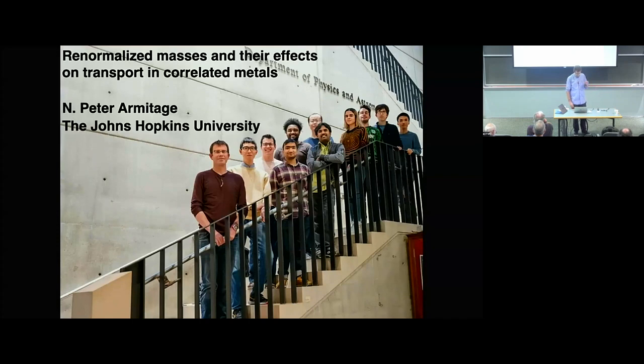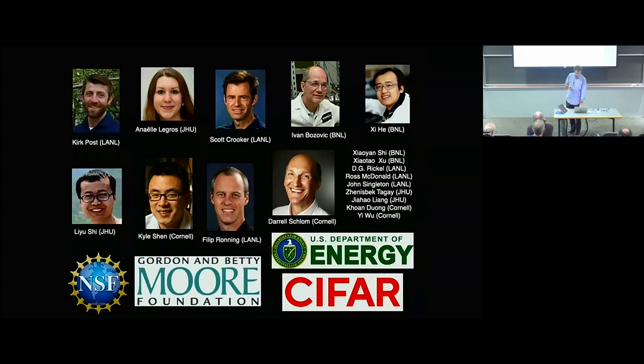And I'm also going to tell you about recent terahertz spectroscopy measurements that we've done on a heavy fermion material, cerium cobalt indium 5. And point out that measurements of the very low frequency conductivity reveal features that show that this system can be interpreted as being consistent with being a Fermi-liquid despite linear in T resistivity. Okay, before I do that, let me thank the various people that made this possible.